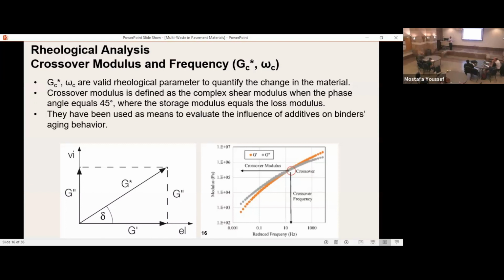If this is 45, through the addition of these additives, a shift in the value of the frequency at this degree, or a shift in the value of the modulus at this level, indicates a fundamental change in the rheology of the material. And the type of shift indicates if it's an improvement or not. So we looked at the crossover modulus and the crossover frequency of our additives as a one unit product, this rejuvenator and the off-spec ash.